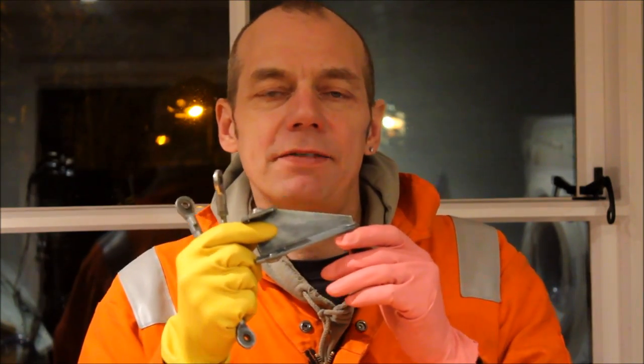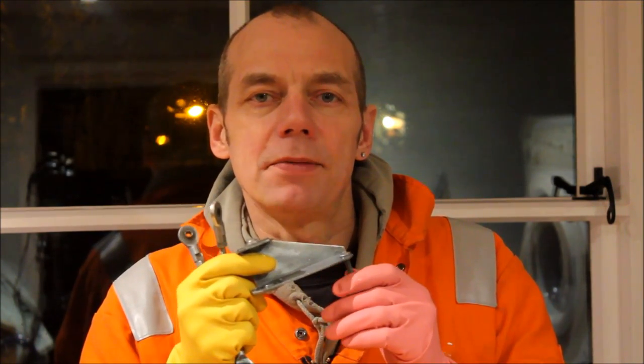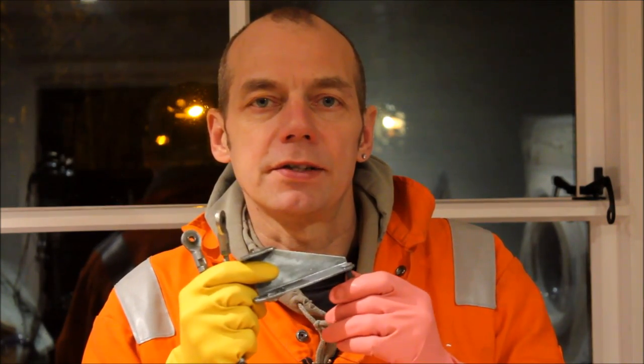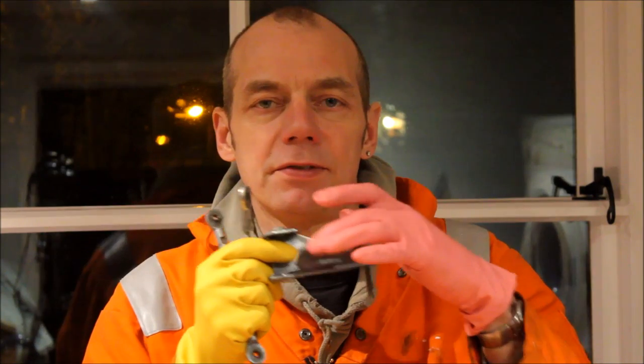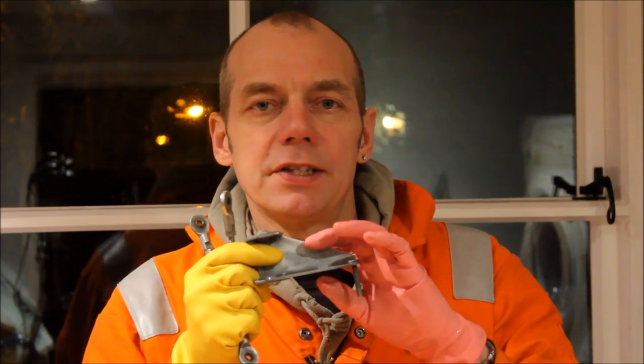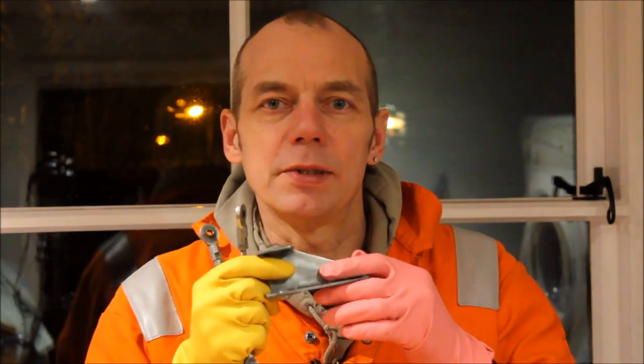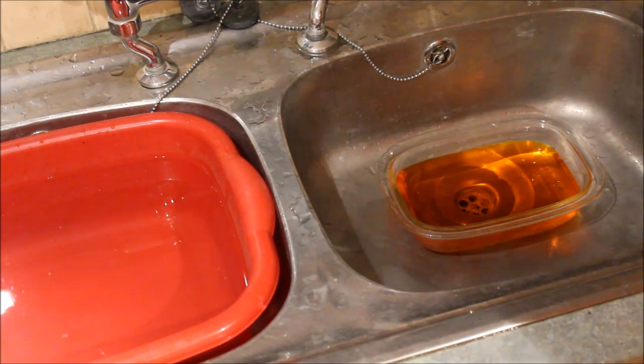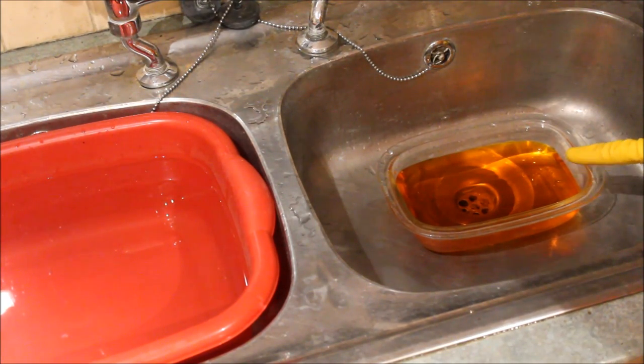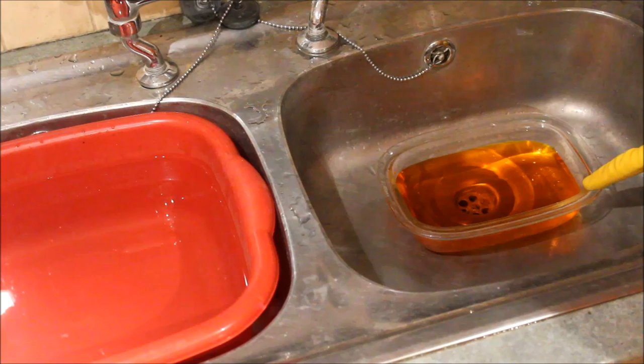Now with the passivation, what we're doing is we're going to dip them into a solution which is rich in chromate ions. And so that chrome will diffuse into the surface there. And that'll mean that rather than zinc oxide forming on the surface, it'll be chromium oxide that forms on the surface, which has just got a more attractive patina basically. Now you can get a variety of different coloured passivates, but this is a yellow passivate that we are using.